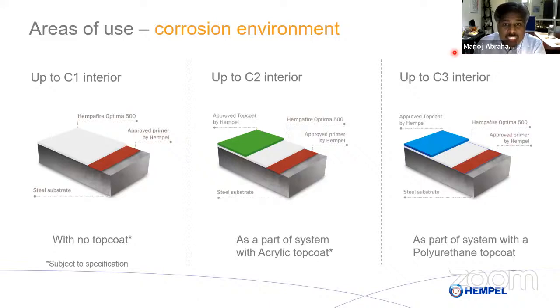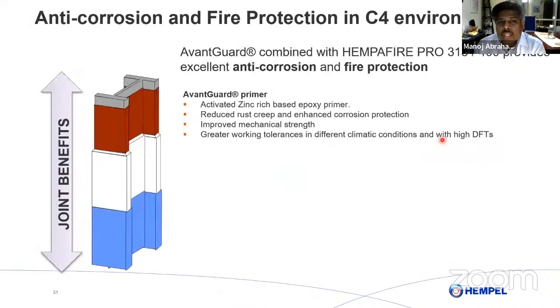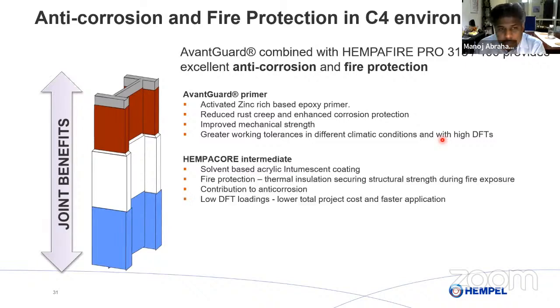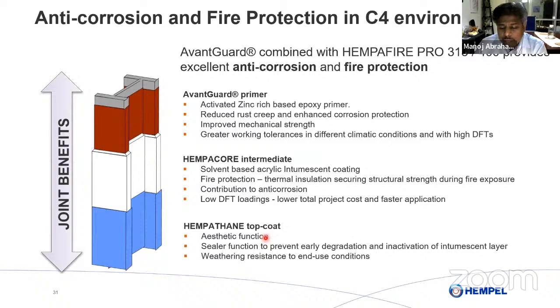But if it is a C3, the steel is internal, but it is not in the air-conditioned or heated envelope. It is outside, subject to a lot of humidity and possible corrosion. Then we would recommend that you put a polyurethane top coat, one single coat of polyurethane at 100 microns. If it is in a C4 environment, then you might want to add a zinc rich primer, and then you put your intumescent, a solvent based intumescent, and then a top coat. So this is what we do.